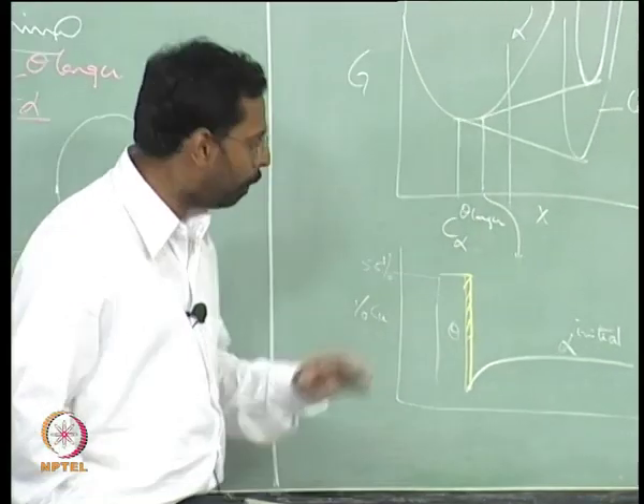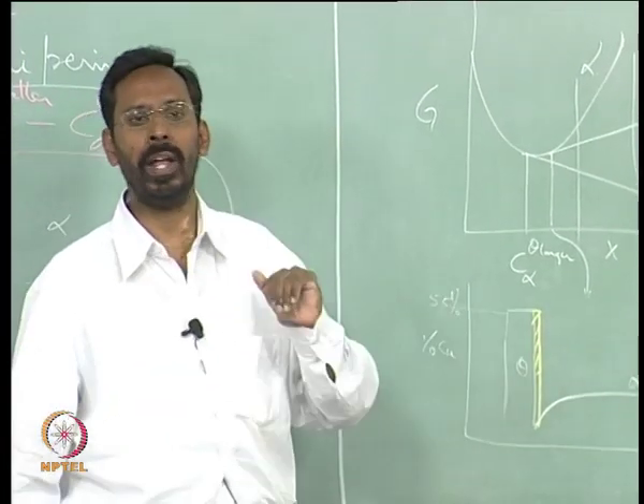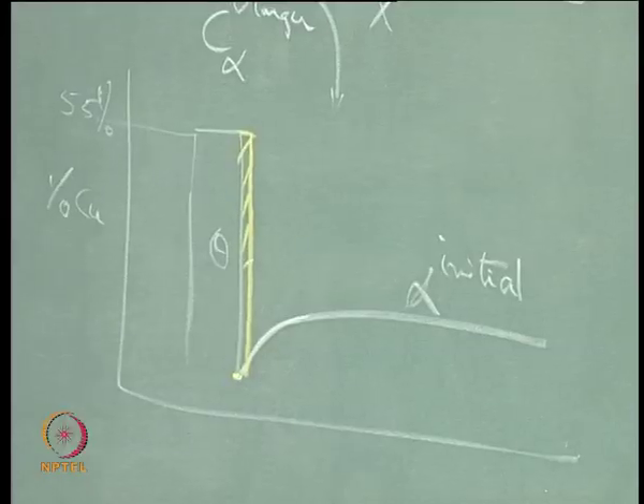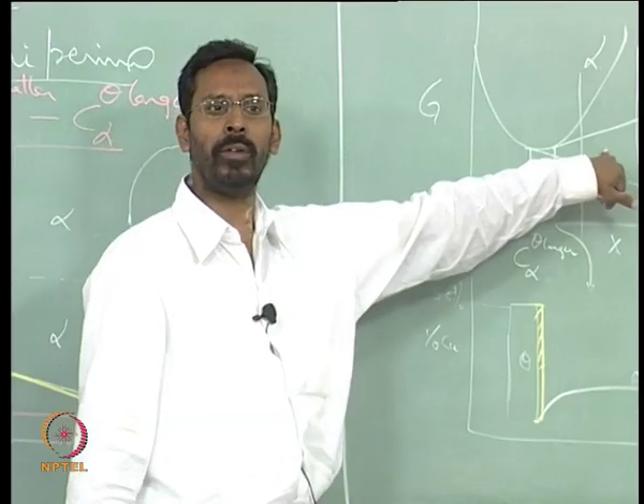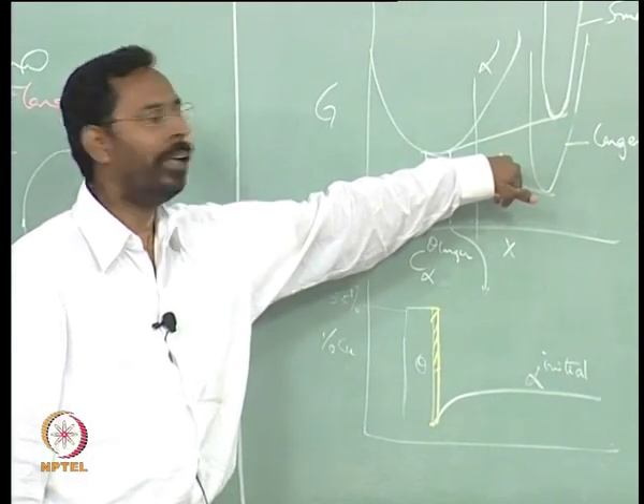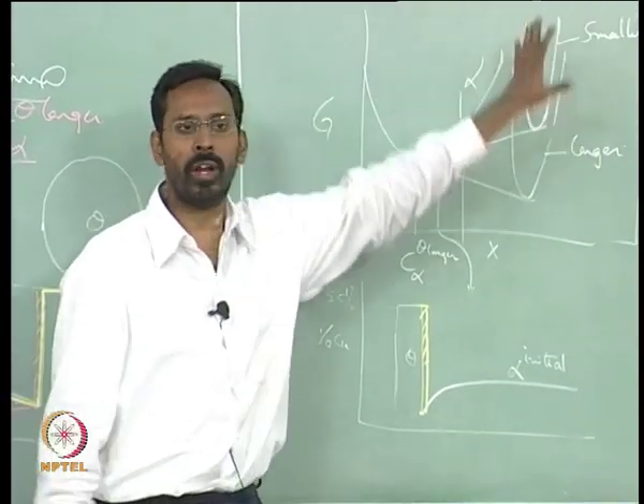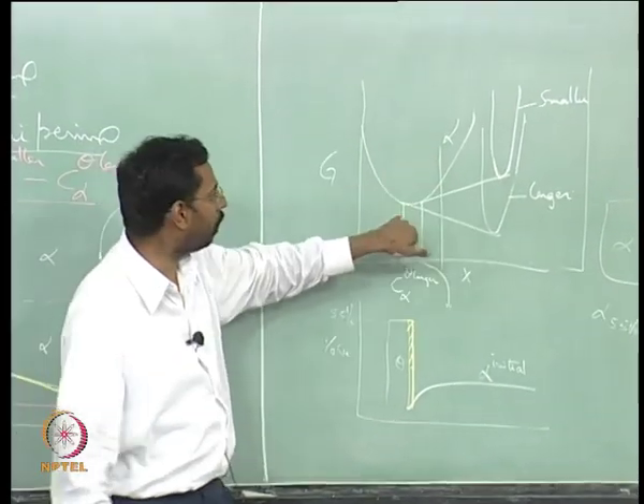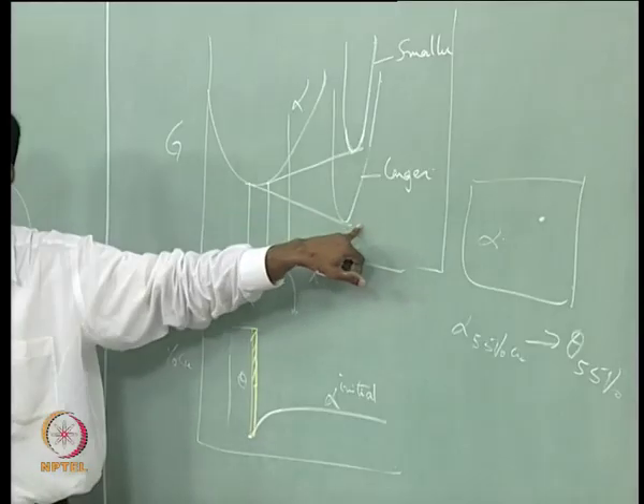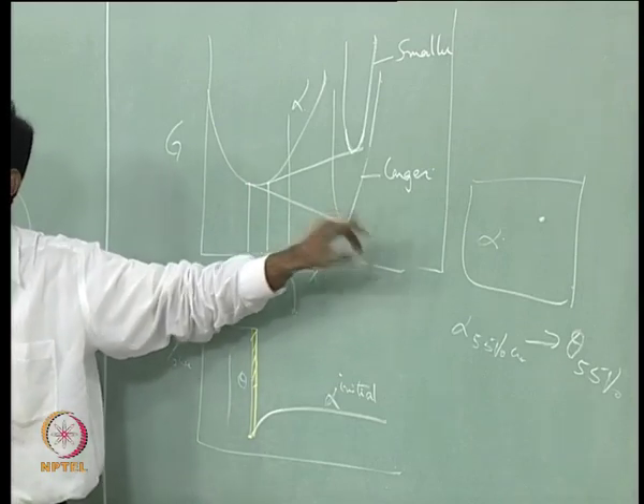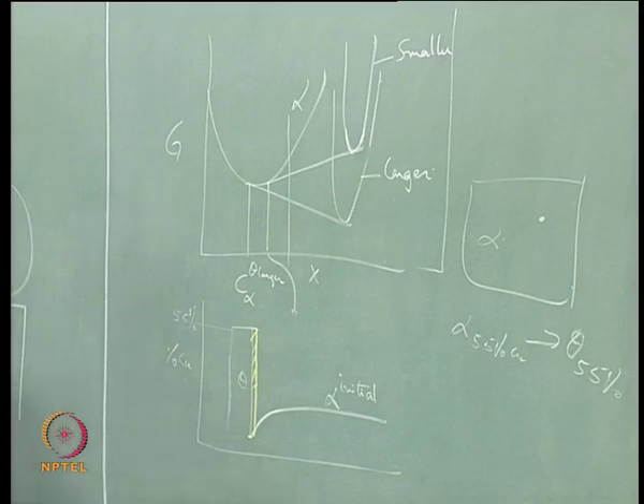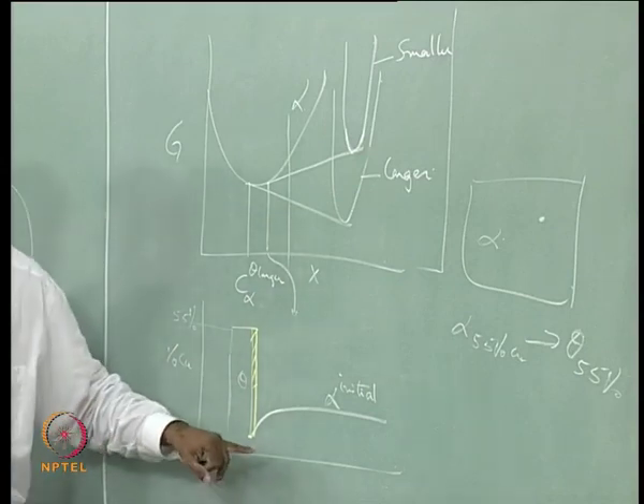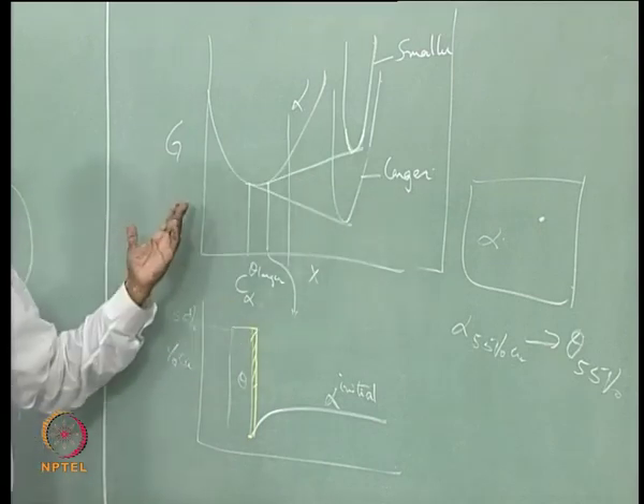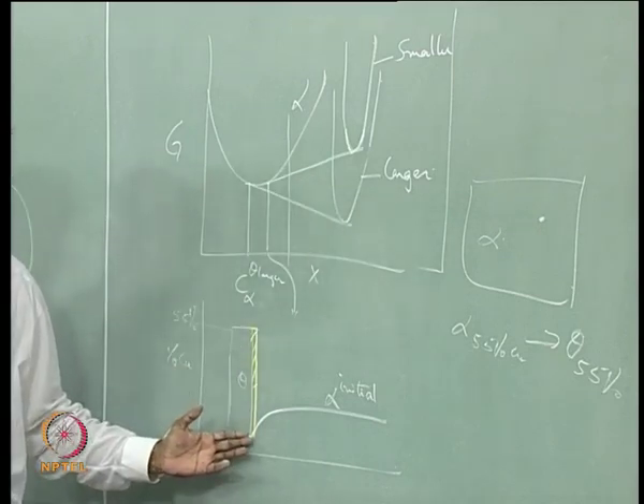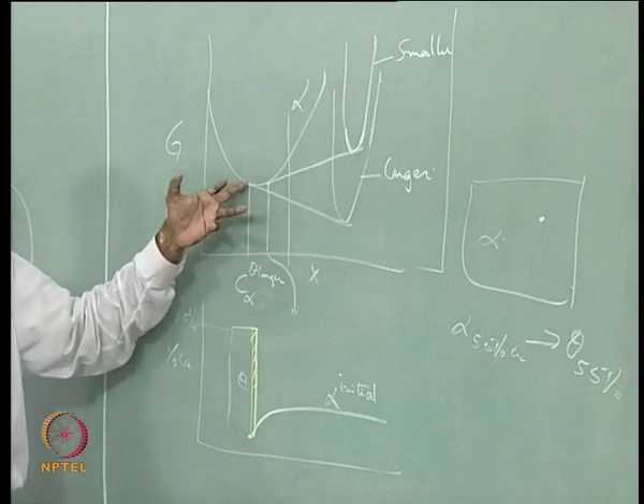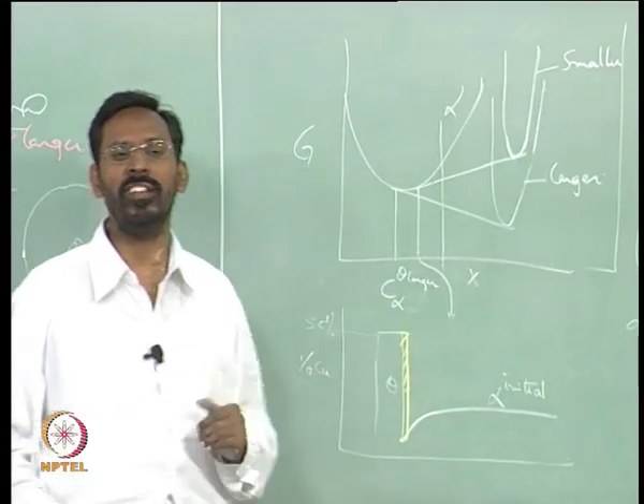But in the whole process, because the whole precipitation is happening at a fixed temperature, this value will never change, because this value is coming from the free energy diagram, and the free energy diagrams are always drawn at a fixed temperature. At a fixed temperature the composition of alpha in equilibrium with theta is fixed, provided the theta size has not changed to such a significant extent that its value can change. If the theta size changes, we can expect that this value also can change, otherwise you can say this value is fixed.